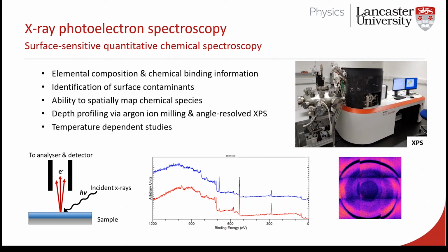We provide an X-ray illumination, an X-ray spot, and that can be down to about a 15 micron spot size in this system. And that X-ray excites the electrons in the chemicals on our sample. They get ejected. We can pick up those electrons that are ejected. And by measuring the energy that those electrons are ejected with, we can very precisely say what the chemical environment was they came from. So precisely that we can distinguish between a carbon-carbon bond, for example, or a carbon-nitrogen bond, or a carbon double bond carbon. Really very incredibly precise chemical mapping capabilities.